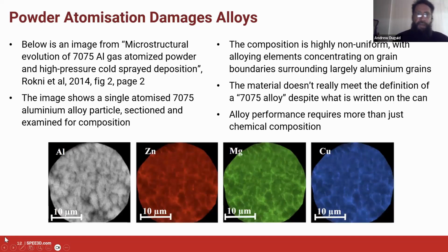Okay, so powder acquisition is a non-trivial step for us, and indeed the whole theory of our alloys is complicated because of this basic thing. So we've got a slide here that talks about why it's hard to cold spray highly alloyed materials as a general rule. And so we start out with a little bit of theory. The metallurgists in the room will be familiar with alloy segregation or Scheil solidification. That's what we're seeing in these images here.